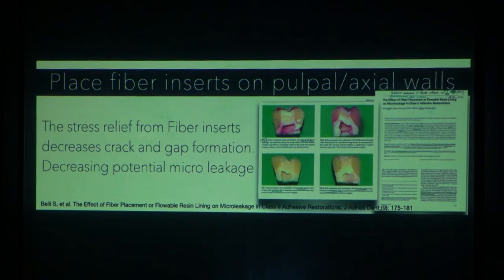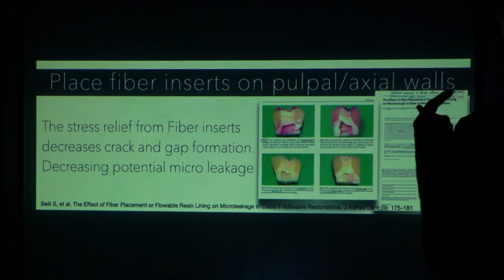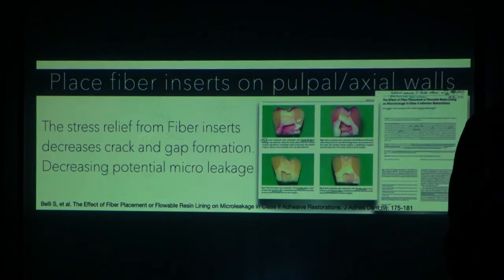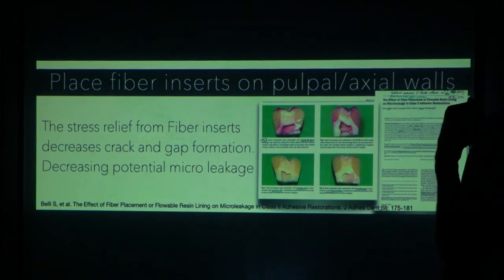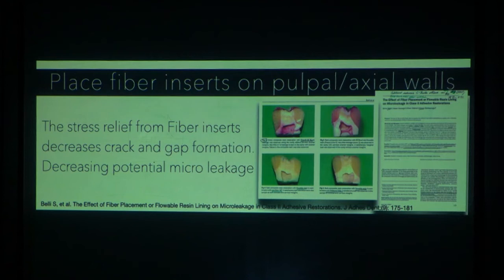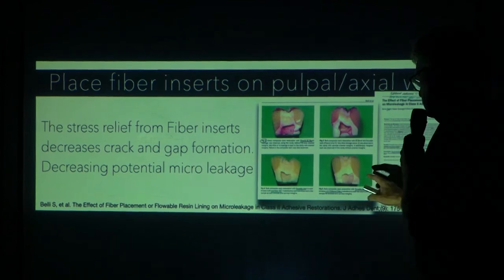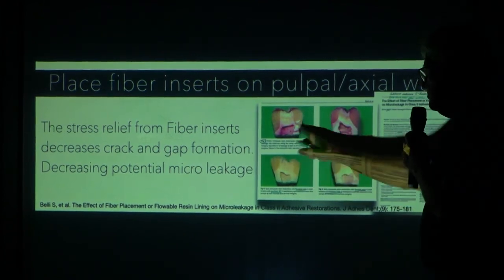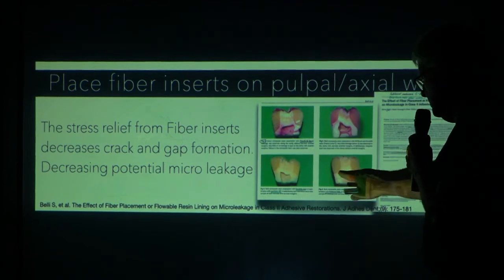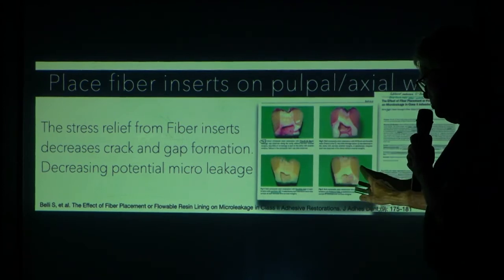Placing fiber in a restoration to preserve the bond strength of the hybrid layer is a scientifically established principle in 3 different continents out of 5 different labs from highly respected researchers, and their research is published in journals. If you read English, you can read these. This paper that was published in 2007 by Semabelli showed that placing fiber means that you can have a leak-free restoration even in a bulk fill. These composite DOs and MOs were bulk filled.